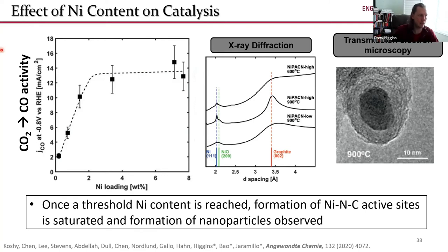And the reason we didn't see that is because these nickel particles would form, but metallic nickel particles are actually a good catalyst for the graphitization of various carbon materials. So what happened is these nickel particles would form, and then they'd catalyze the growth of this graphitic shell around them. And what that graphitic shell did is it essentially blocked the surface of those nickel particles from doing any catalysis under CO2 reduction conditions.